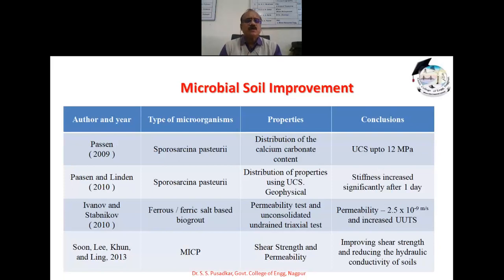I am just showing you some of the bacteria which have been referred to in the literature by various authors, and how the soil properties have been improved. With Sporosarcina pasteurii, the UCS has increased up to 12 MPa because the strength improved with the formation of calcium carbonate. Then another author has used Sporosarcina pasteurii, and the stiffness increased significantly after only 1 day. When I use a ferrous or ferric salt based biogrout, the permeability is reduced to a great extent.